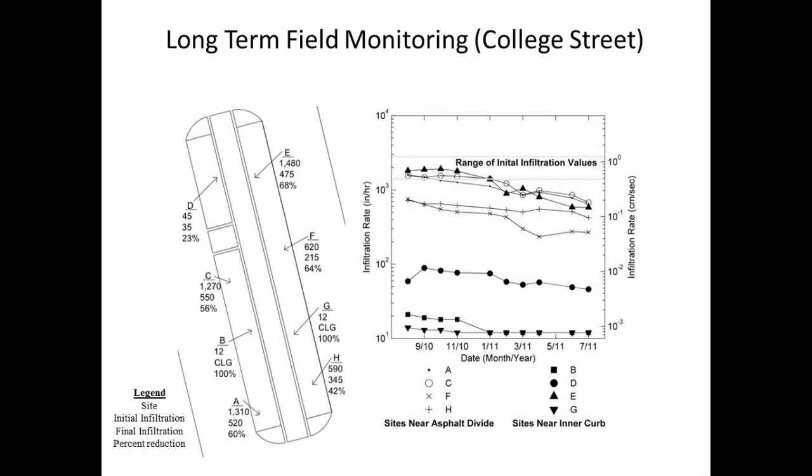So what is the typical infiltration rate that will be needed to accommodate, let's say, a 100-year storm, just to put things in perspective? Sure. Well, as you can see, these would be magnitudes greater than any storm you would see if you had a direct rainfall on top of it. This is 10 inches per hour, and all of these are accommodating that perfectly well. If we had 10 inches per hour, we'd be standing in water. So they have much higher infiltration capacities because we've been able to keep these lots clean.